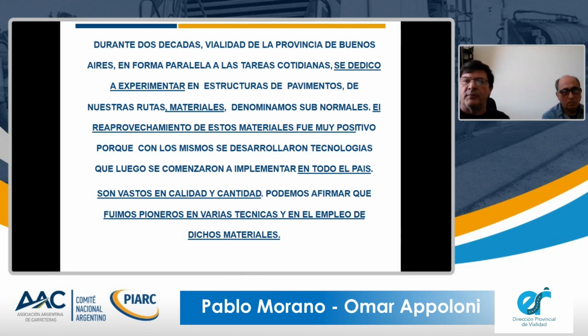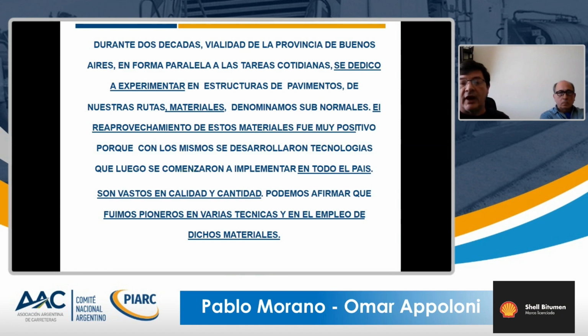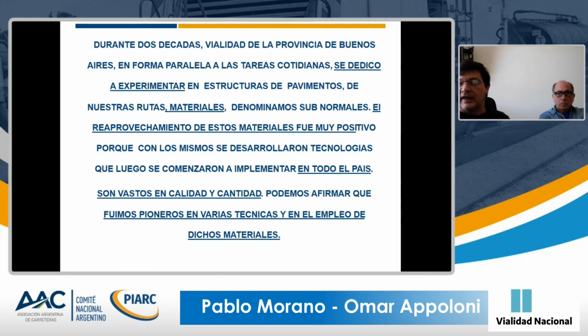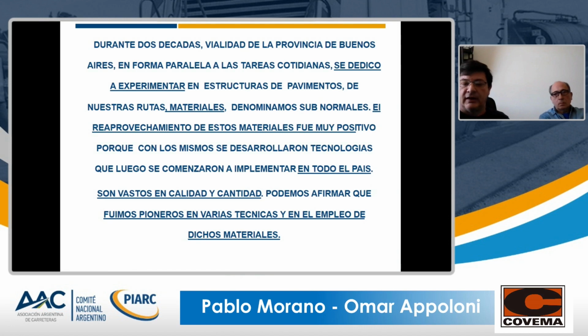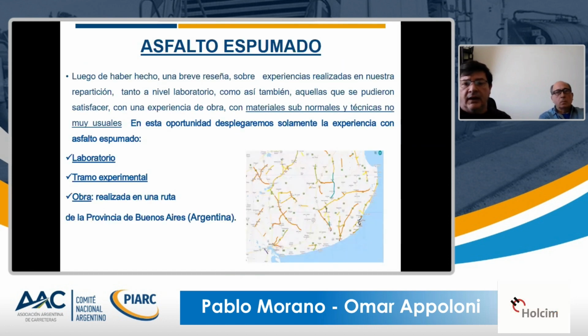and after that we used this as the structural layer, as a subbase in an actual road. So in these 2 decades we have used many substandard or non-standard materials, and among them foamed asphalts. The RAP production is abundant, so we try to use it as best possible, knowing the potential of that material and the environmental damages that we sometimes cause when we use virgin material. So the idea here is to take advantage of this reused material, which was used at 100%. Here we have the province of Buenos Aires. We have more than 10,000 kilometers of paved roads, and we have different possibilities of use.